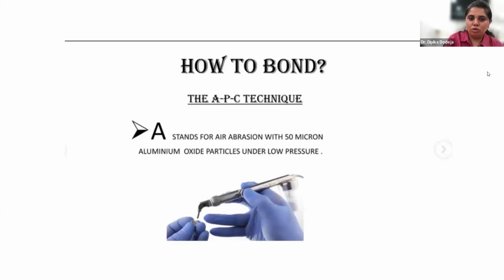How do we bond to zirconia? It is called the APC technique, where A stands for air abrasion, P stands for primer, and C stands for the cement. Since we are not etching the zirconia, how do we create those micromechanical areas to bond to? Air particle abrasion with 50 micron alumina under low pressure is what is used to make those micromechanical retention areas.